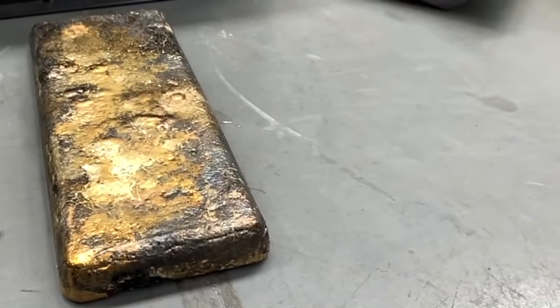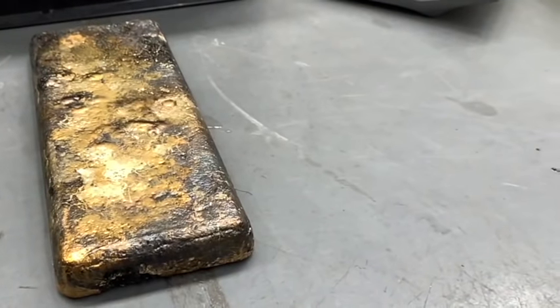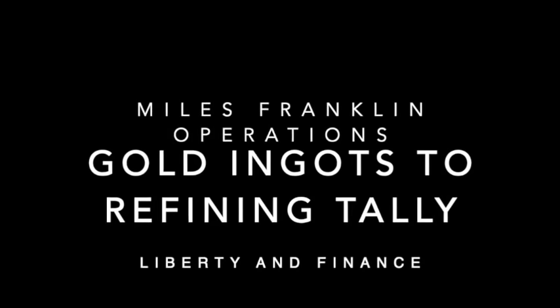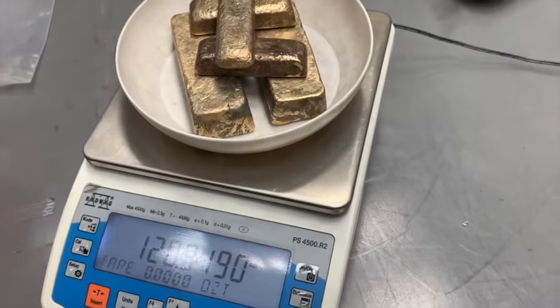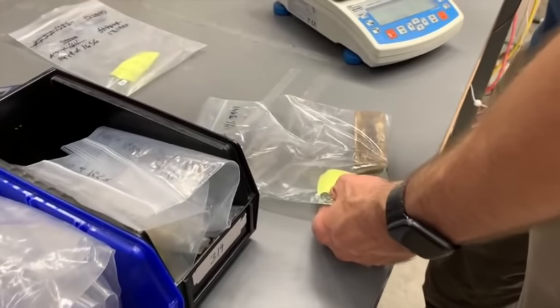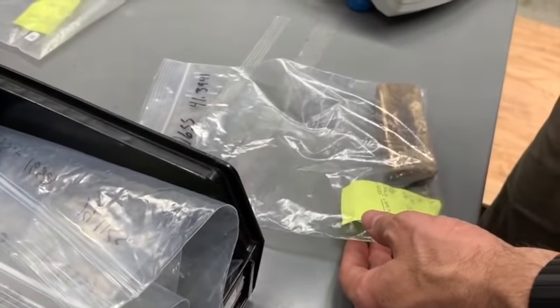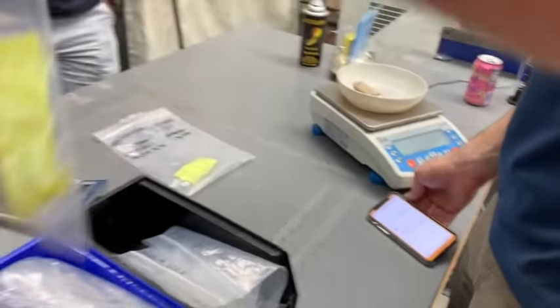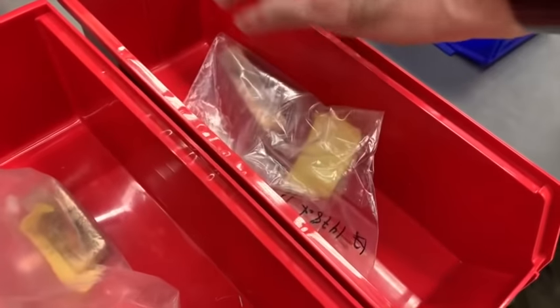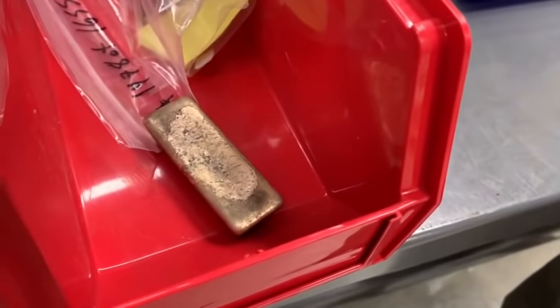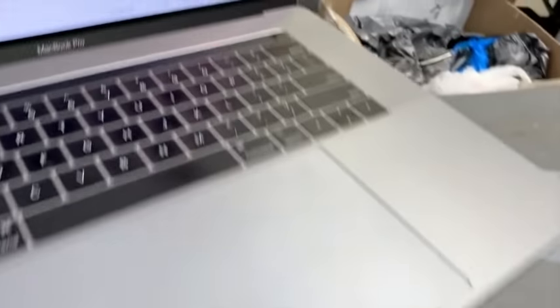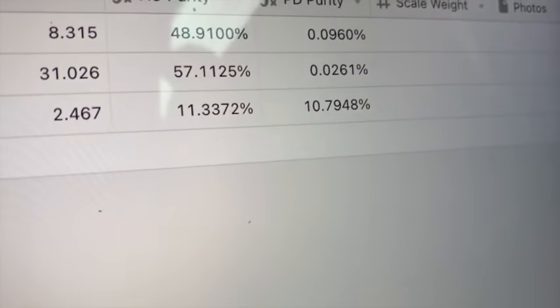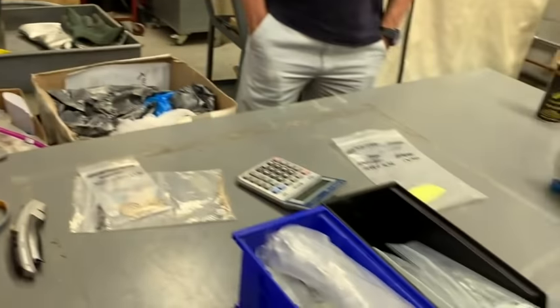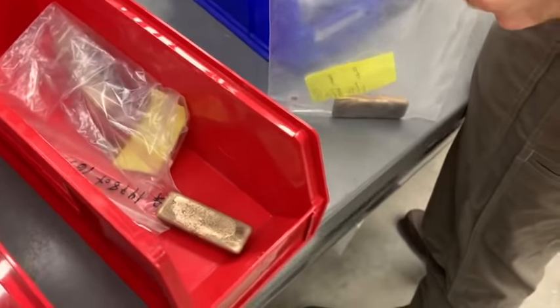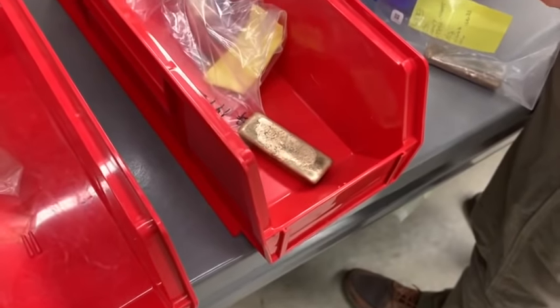There the ingot is awaiting final analysis and final weighing before being added to a batch of gold ingots sent to refining. Here are smaller gold ingots that are being combined into a batch, and additional ingots are being measured. What is the purity of those, roughly? Well, so far, stuff that's in this batch, the net purity is 57.1125 out of those two bars. We'll actually see that number adjust as I add bars to it as a weighted average. So now I'm going to add another one to lot number 330.